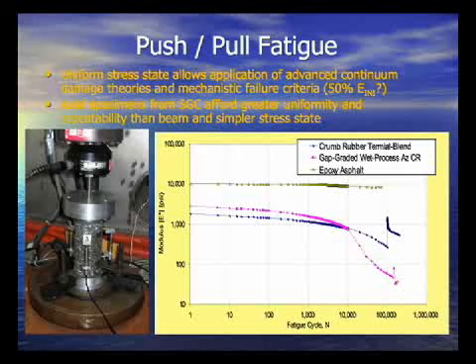If you look at what we use as a 50% reduction in modulus, I don't know how realistic that is. If you look at some of these mixes that we've started looking at, you can get quite a lot of reduction in modulus, but they're still performing before you get to a crack, a macro crack.